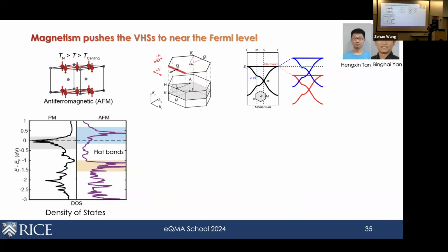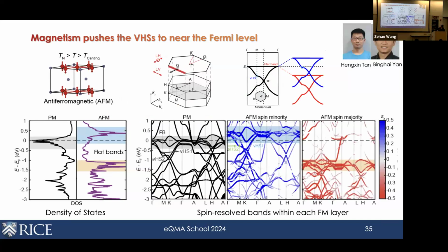So again, let me show you how we understand the magnetic order here. The story is essentially the same as iron tin, because they're isostructural, they have the same magnetic structure. If you do the DFT calculation, the exact same thing is seen, which is that you can consider each layer as a ferromagnetic layer, and then they split into spin majority and spin minority states. Fine, great. The interesting thing for this one is that if you look at where the Van Hove singularities lie, when you have the flat band here, then your Van Hove points necessarily must be farther below the Fermi level, right? So the interesting thing here is that when we split into the spin majority and spin minority states, the Van Hove singularity from the spin minority states actually gets levitated towards the Fermi level, and you can track that here in the DFT calculations, right?